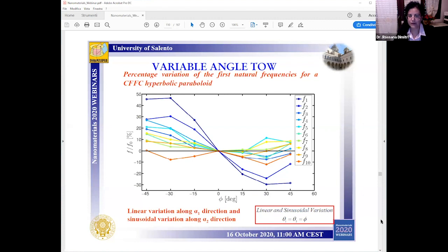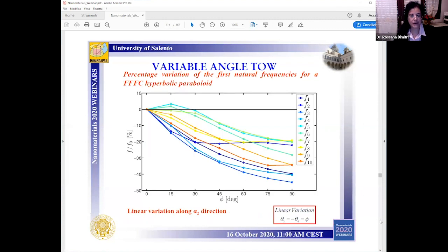Respectively. So here the response varies when we assume just a linear variation of the fiber orientation along alpha 2, with a clear decrease of each frequency for an increasing value of phi from 0 up to 90 degrees.